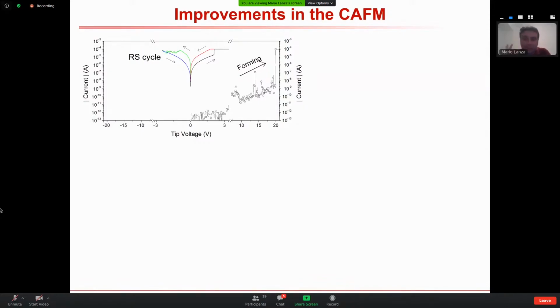At the same time, I have to say that there are some materials, for example mechanically exfoliated boron nitride, that show a little bit different breakdown phenomenon. When you apply the dielectric breakdown, it normally produces one crater, one explosion. In this material there is physical removal of material. You make a hole, so that is a destructive breakdown event. It was published in ACS Nano in 2015 by Professor Keisuke Nagashio from Japan. This is a little bit different mechanism, because the penetration of defects in the boron nitride only happens at very high energies, and then it's very difficult to control even if you apply current limitation.